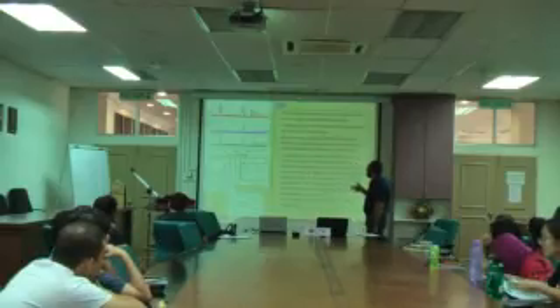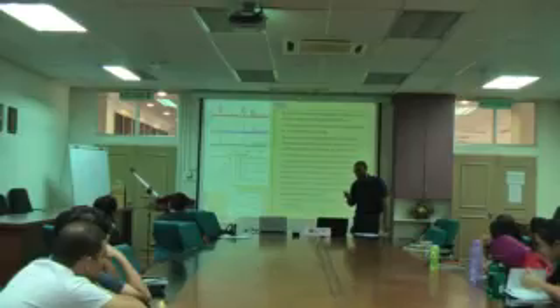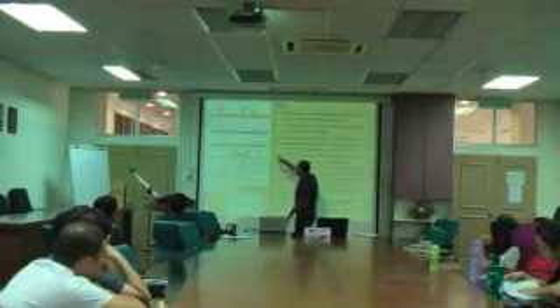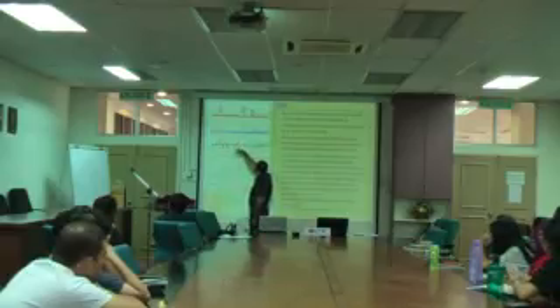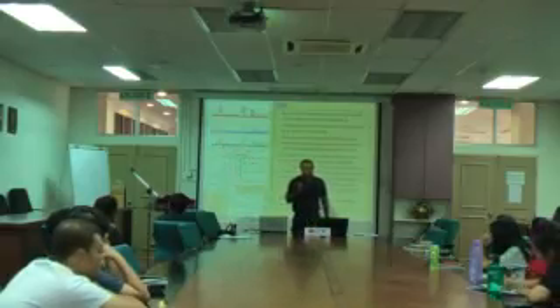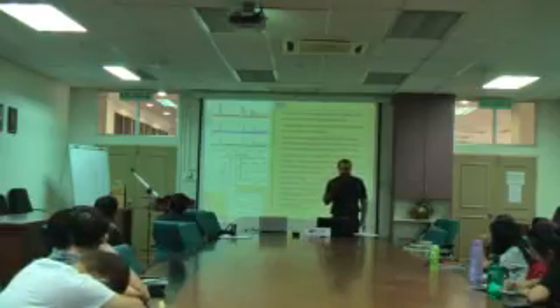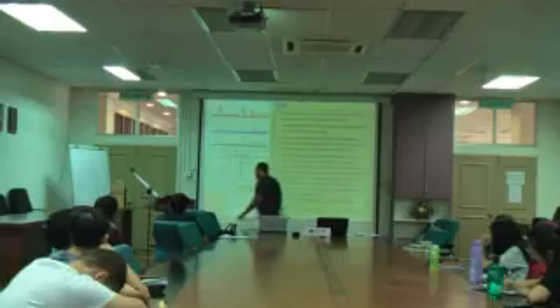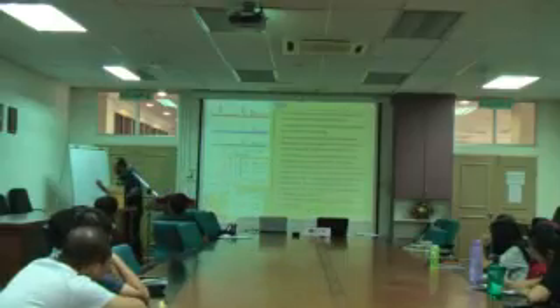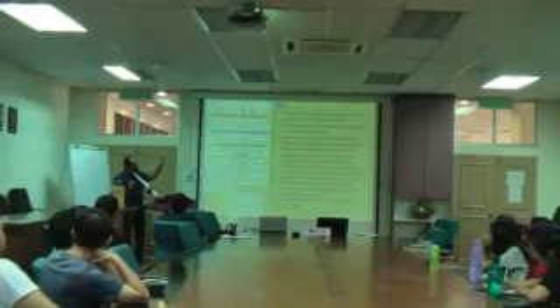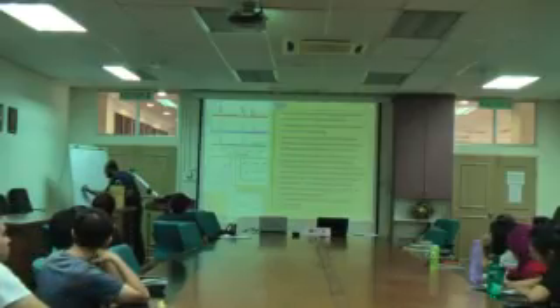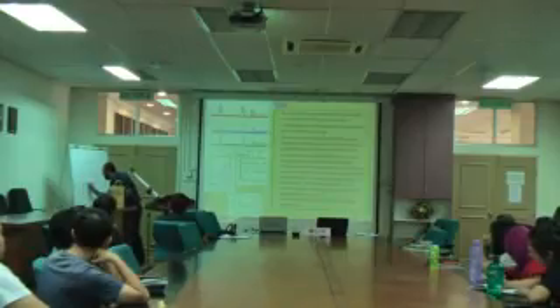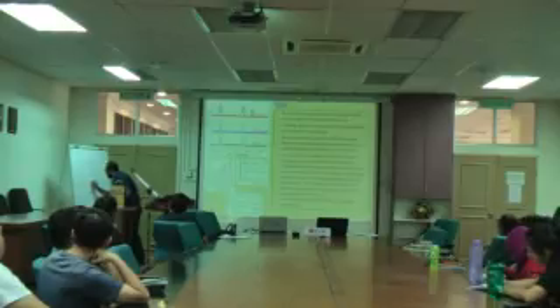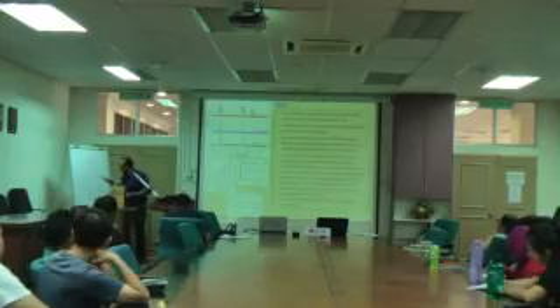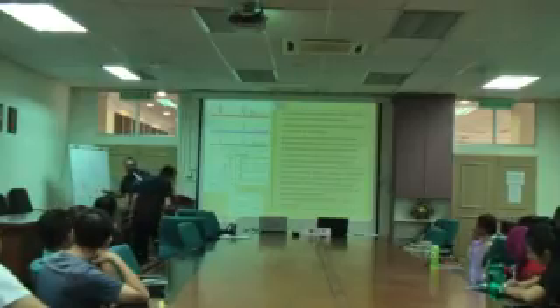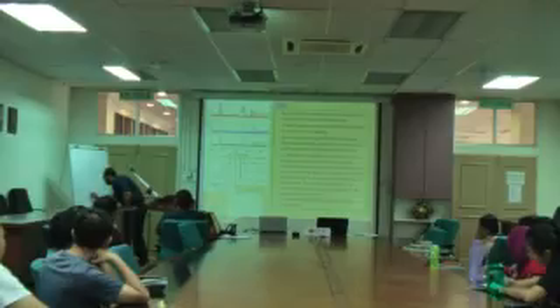More sharper peaks means a higher degree of crystallization. As you can see, the full width at half maximum also decreases. When the full width at half maximum decreases, that means our size increases. Because if I look at the width of the XRD peaks, this is the FWHM. This FWHM experimental, we call beta experimental.